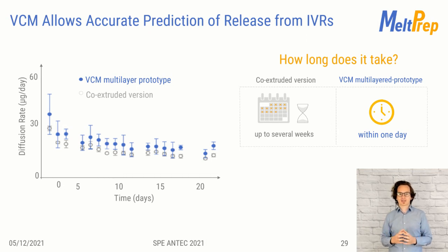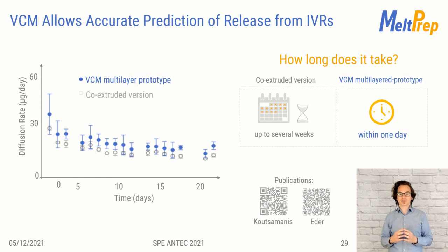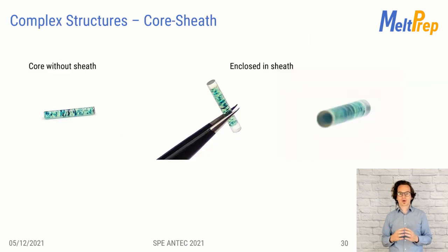Recent developments allow us also to manufacture core sheath structures in less than an hour. A 2 millimeter implant with a length of 10 millimeter is entirely embedded in the sheath. The fusion of pre-manufactured samples is the base for the sharp interfaces that you can see here.